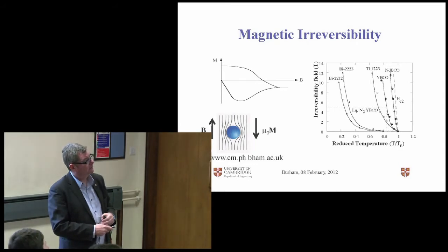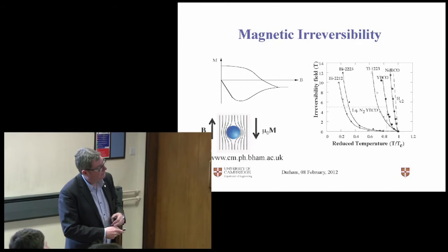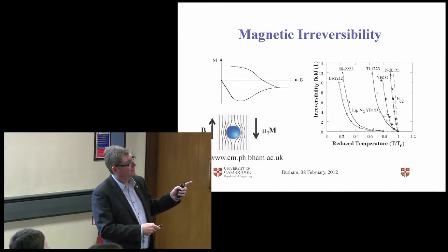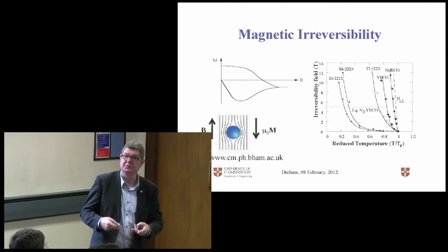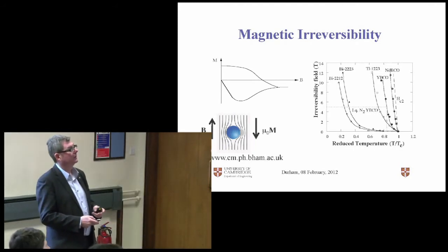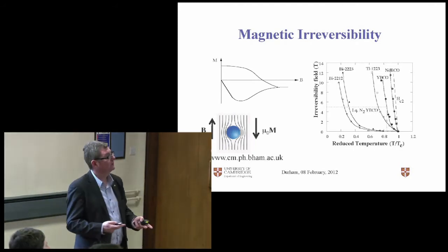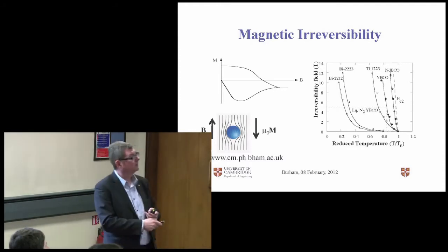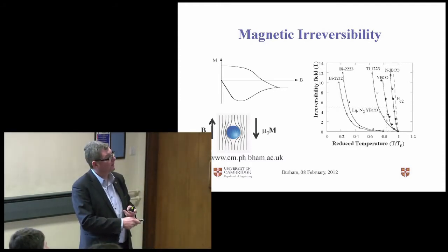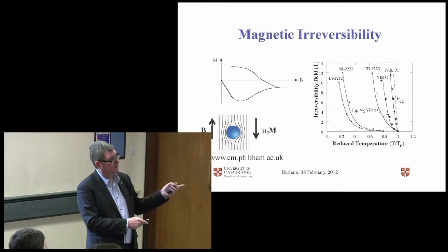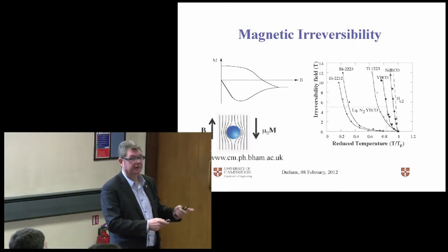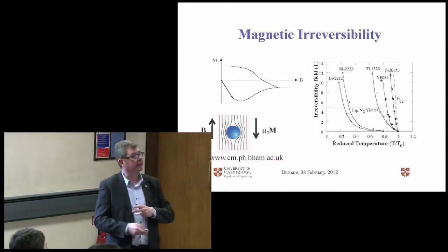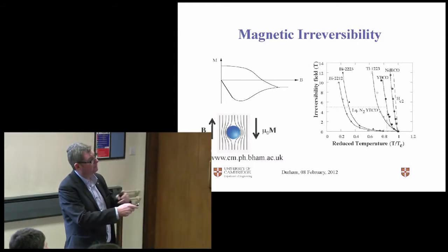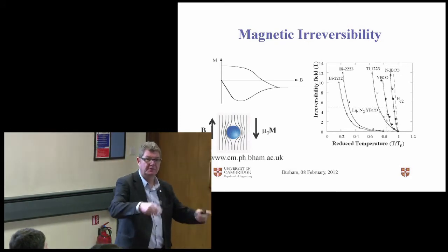And when we decrease the applied field, well actually I should say we get to a point where, as we go to higher and higher field, the Lorentz force, the thing that makes the flux lines move, gets bigger and bigger, and at some point the Lorentz force exceeds the pinning force and our flux lines start to move. And at that point it becomes reversible, so there's no hysteresis, but then when we decrease the field, we return to minimum Lorentz force, we turn that pinning back on, and now flux, having got into the sample, can't get out. So we can decrease the field right to zero. Essentially all we've done is flip the currents, they're flowing the other way.